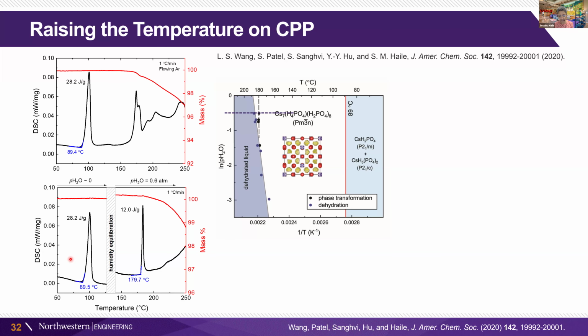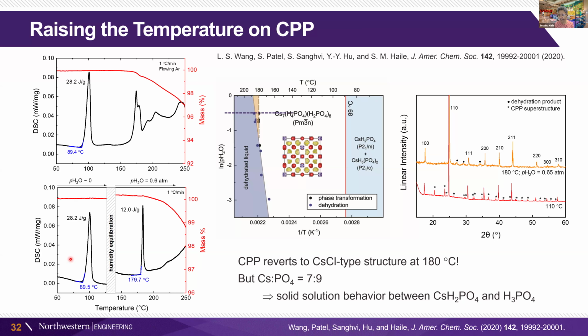Well, I'm not showing it on here. We have first the transition to the formation of the CPP phase, and then that black dotted line is where we transition to a new solid state, which occurs at 180 degrees Celsius, and then the dehydration occurs. And we collected then the diffraction data at 180 degrees Celsius under very high steam, and we can see that